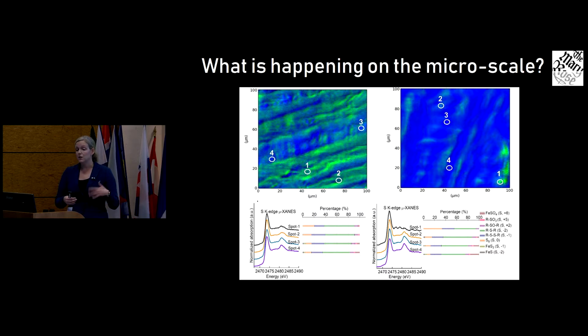So in here, the green on the left is the surface before we started drying, and on the right is after we started drying. The green is the reduced sulfur, and the blue is the oxidized. So you can see straight away that there's much more oxidized sulfur. And then at the points indicated here, we've done XANES to work out exactly what is there. And by also measuring our standards, we can then do quantitative analysis to work out the different proportion of materials that are there. So this is all great.